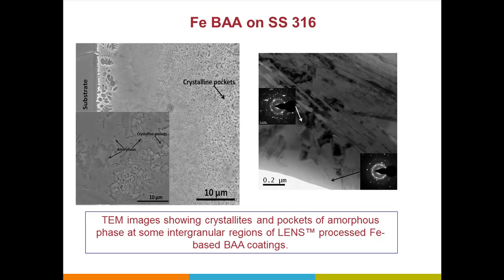I'll only show this in terms of TEM and all these things, but if we look at the high resolution SEM and transmission electron microscopy, we basically preserved the amorphous nature of this composite coating. We did not deteriorate anything. Essentially we have some crystalline pockets - we analyzed the powder and the powder also had crystalline pockets. So LENS processing did not deteriorate anything, it just preserved the entire bulk amorphous nature of this coating. So if we had 100% pure bulk amorphous powder, I think LENS processing will give the product the same way.